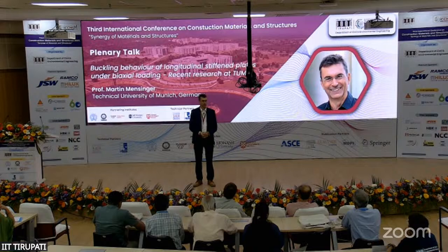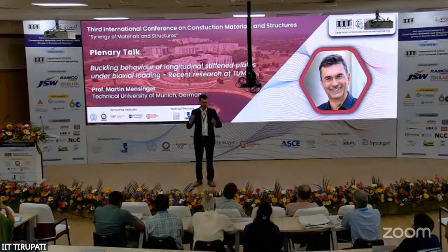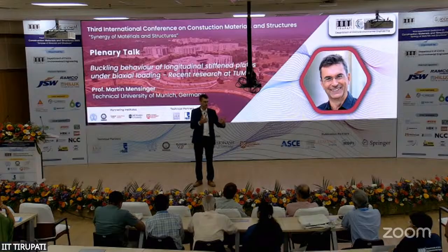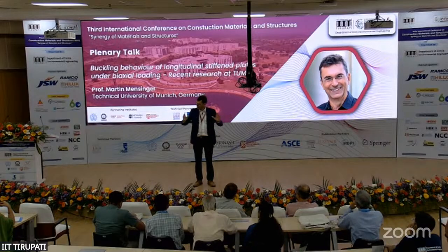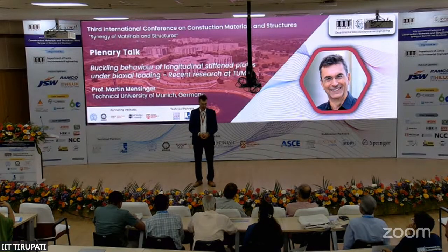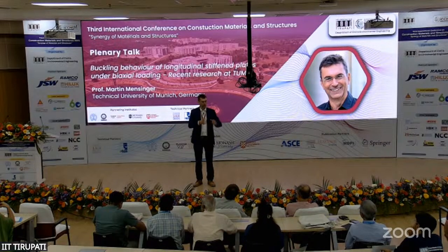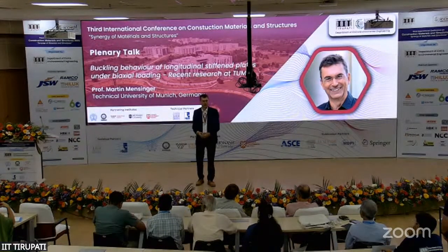Okay, so we have shops, steel contractors. Normally they produce segments in a size they can handle, about 100 to 160 tons, but in this case the segments are transported on the road, and therefore they are limited to perhaps 30 to 40 tons. There is always a concept for prefabrication in the shop, and then the segments are welded on site, and this is supervised with continuous measurement. The owner also normally has consultants who are only for supervising welding quality and the geometry of those bridges.